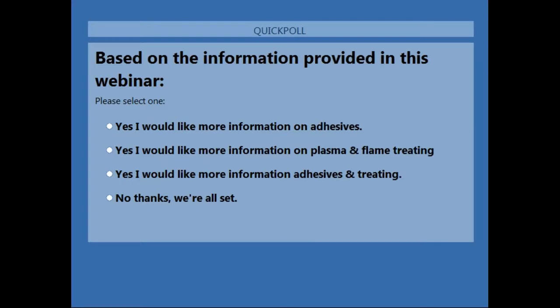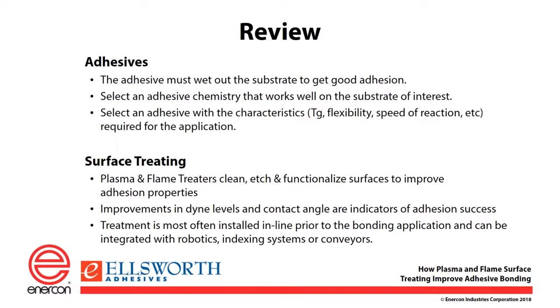So we're going to close that poll, and we're going to move on to our review. So we learned today that adhesive must wet out the substrate to achieve proper adhesion. We've looked at the importance of making sure you have the right adhesive chemistry that's going to work well with the specific substrates that you are going to be bonding to. We looked at the specific characteristics adhesives need to have required for the ultimate application of the adhesive. We've seen from the surface treating side of things how plasma and flame treaters can clean, etch, and functionalize surfaces to improve their adhesion properties. We've learned that dyne levels and contact angles are indicators of adhesion success. We also looked at many applications and found that treatment is most often installed in line prior to the bonding application and can be integrated with robotics, indexing systems, or conveyors.